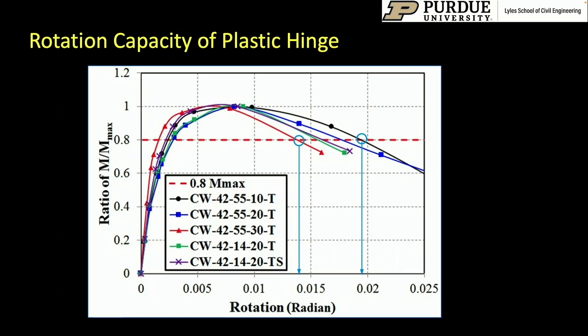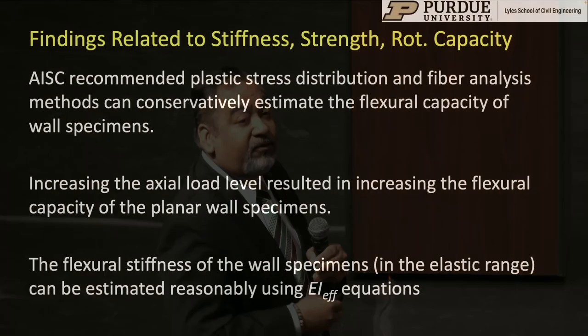I'm showing you here results from about 5 different tests that are showing the ratio of the moment with respect to the plastic rotation capacity of the hinge at the base, showing rotation capacities that were in the neighborhood of about 0.015 or about 0.02. And as the axial load increases, the rotation capacity decreases ever so slightly. So we were able to use all this information from the research in order to verify the equations for stiffness and the equations for strength.